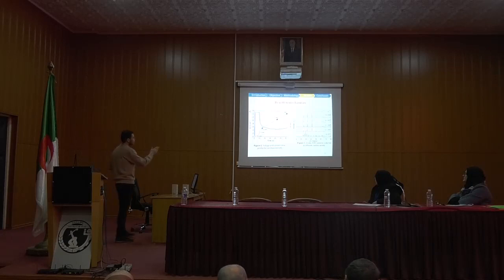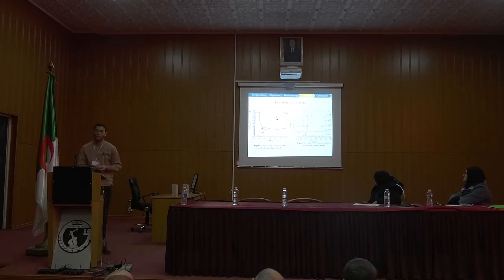We apply a current to the sample, and then we record. We did the X-ray diffraction for different points of the sample. At the beginning we see that the X-ray shows that only the raw materials are present in the sample. Step by step we see that we move to the formation of zirconium diboride material, until at the end we reach a phase pure diboride material. So you can see here the evolution of the X-ray until finally we get our final product.